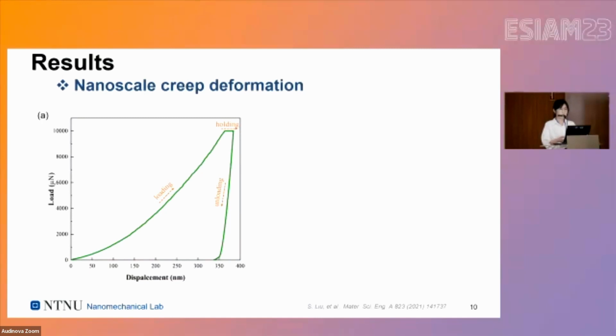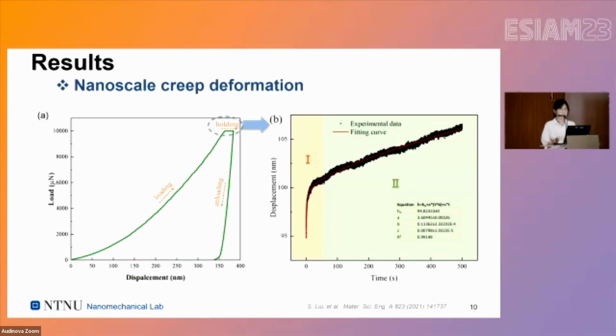Another property we are interested in is the creep behavior. From this holding stage, we can obtain the creep displacement as a function of creep time. We can see that in this curve, there are two distinct stages. At the first stage, the creep displacement increases rapidly, and then the increase rate tends to be constant. Then it tends to the steady state stage.